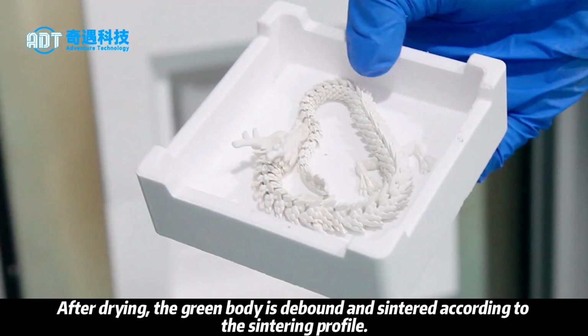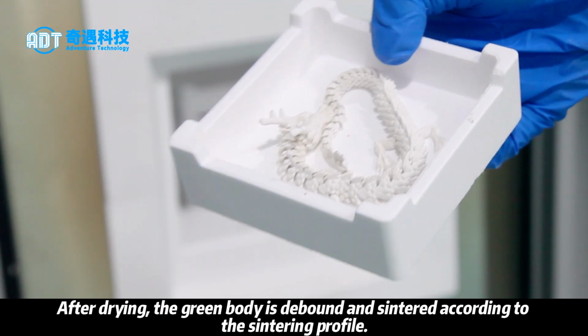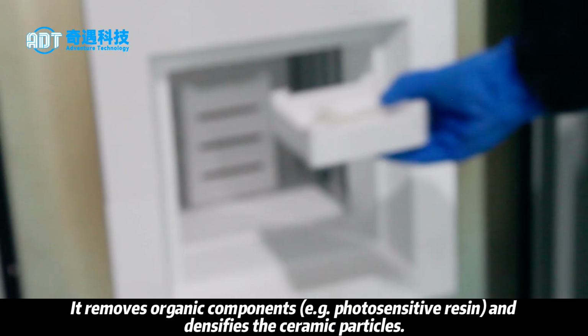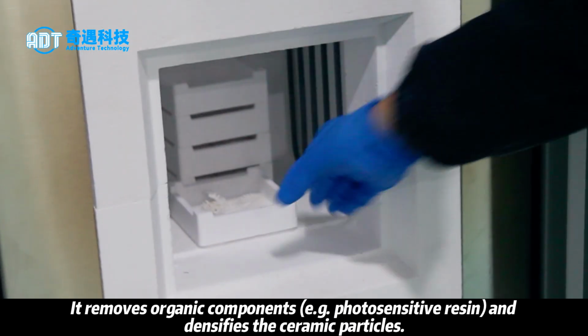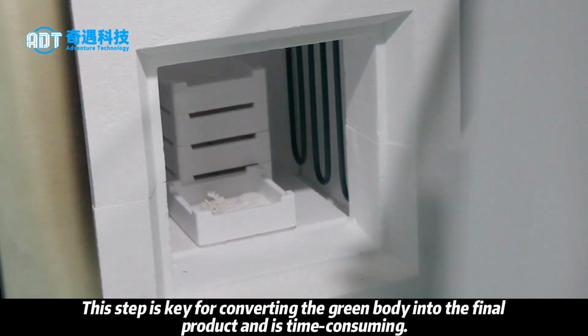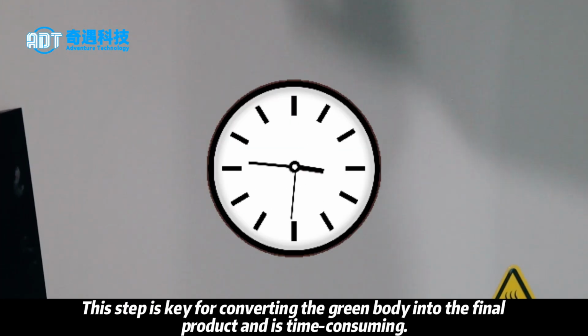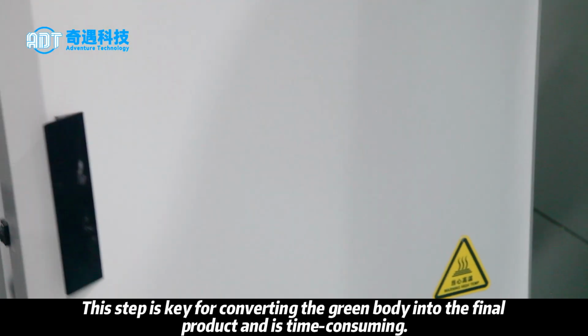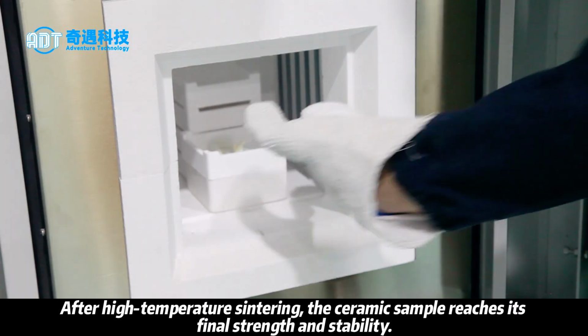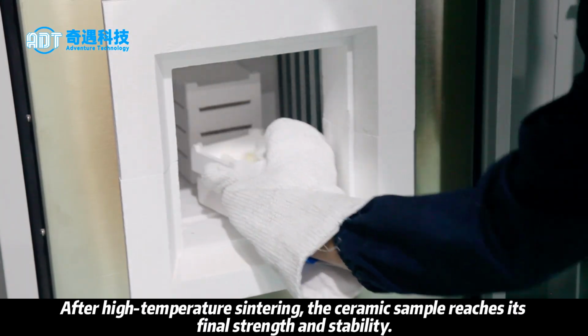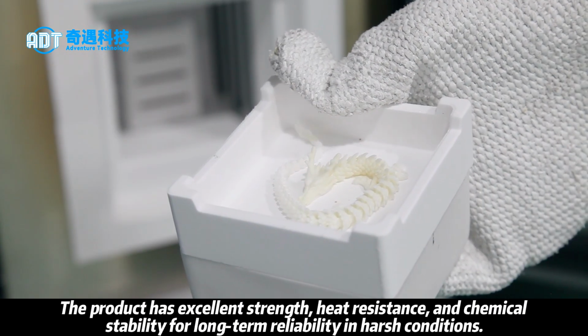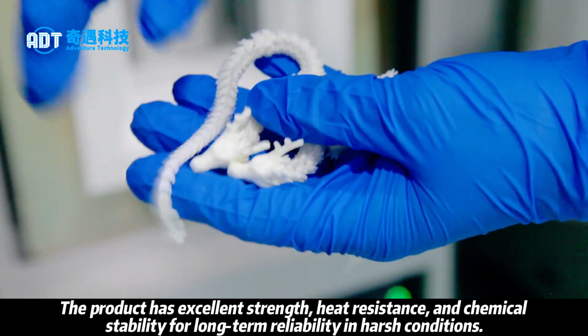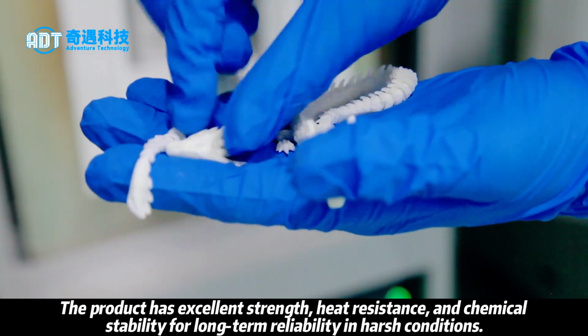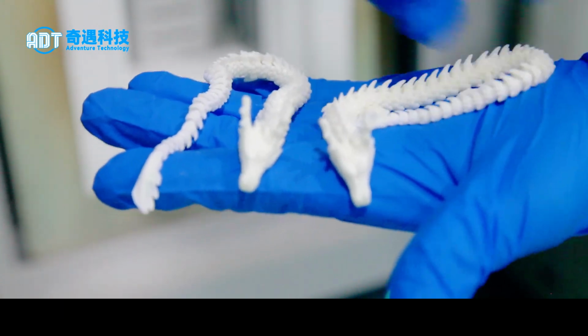After drying, the green body is debound and sintered according to the sintering profile. It removes organic components and densifies the ceramic particles. This step is key for converting the green body into the final product and is time-consuming. After high-temperature sintering, the ceramic sample reaches its final strength and stability. The product has excellent strength, heat resistance, and chemical stability for long-term reliability in harsh conditions.